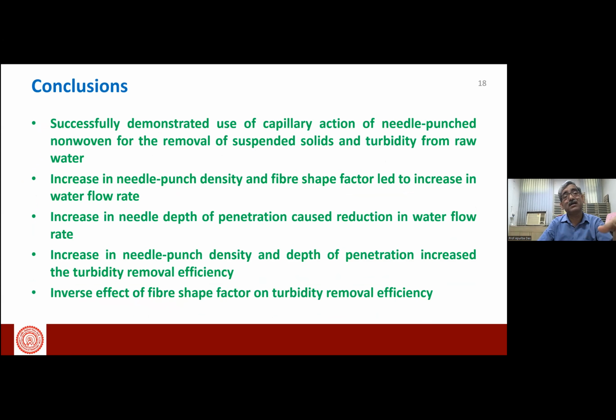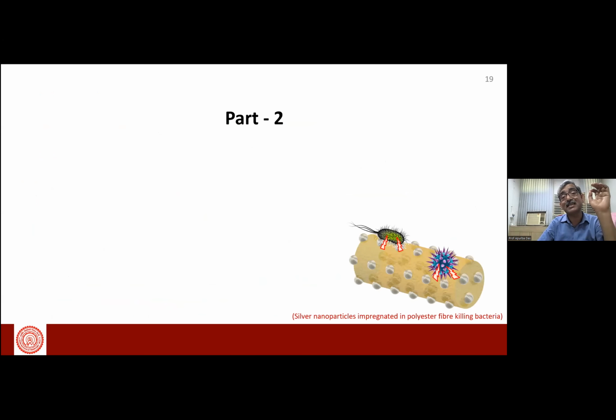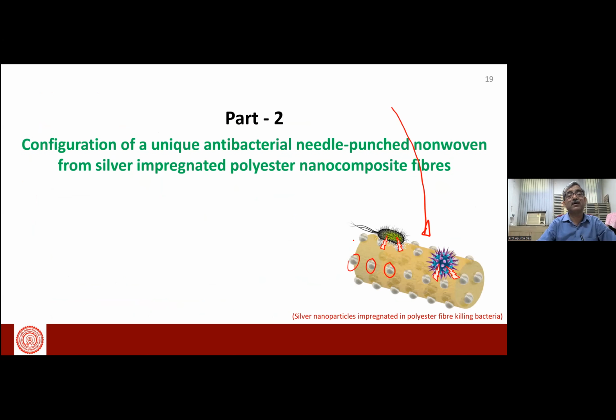Okay, that we have already done. Now in second stage, what we have done, we have used this same parameter, and then we have taken the silver nanoparticle embedded polyester. So here we have configured the unique antibacterial needle punched non-woven. So we have removed the solid particle. Now our focus was to kill the bacteria using the silver nanoparticles.